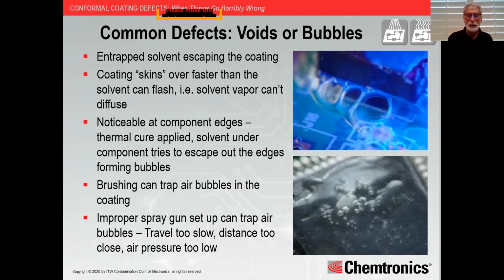If you're using a spray gun, improper setup, or your settings have drifted, they can trap air bubbles. If your travel pass across that board or across that assembly is too slow, it can entrain air as it hits the surface of the board, okay? Possibly air that's underneath that component that we just talked about. If the distance between your nozzle and your substrate is too close, now you've introduced some turbulence in that coating as that higher pressure coating hits that surface, and that can trap bubbles.